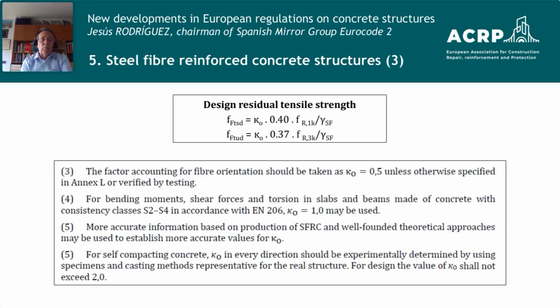And with these values, it is possible to introduce them in the different calculations of this type of concrete. Well, one interesting topic, at least from my experience, is that there is going to be an approach to consider the fiber orientation. So in the use of reinforced concrete with fibers, there are at least two concerns. One is if we have the amount of fiber required, and the second one, if the distribution and the orientation of this fiber is adequate.